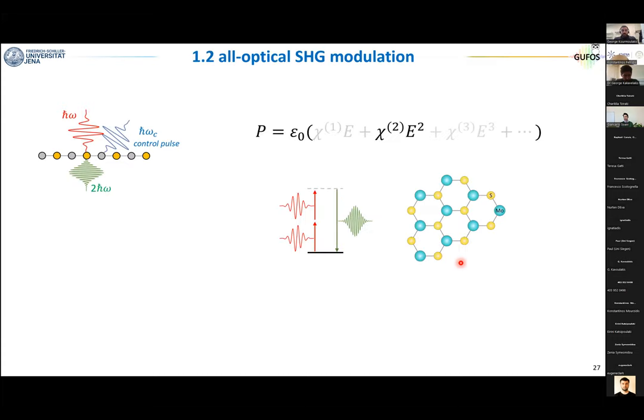Now, the idea is very similar. We again want to have a modulator, so a device where we switch on and off the nonlinearities. This time, we will be looking at the second harmonic because, again, as I said, we have a hexagon, but the two atoms in the hexagon now are different, so the space inversion symmetry is broken. In this case, we can have a chi2. We can do second harmonic generation, so we enter with two photons, generate one photon at two omega.